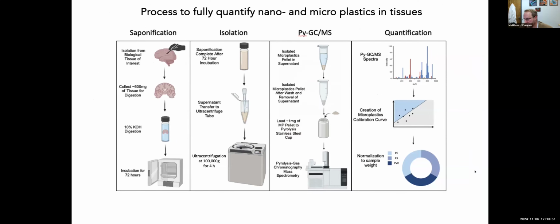So we developed a more cumulative approach for capturing all of the plastics independent of size, using a spectrometric method to do this. If you're familiar with Breaking Bad, the TV show about New Mexico, this is what we do to tissues out here. We put them into either an acid or a base, and we digest everything away that is biological. Essentially, we're using potassium hydroxide, turning the tissues into soap. We then spin out the solid remaining particulates, which is plastic and some small rocks, but mostly plastic. And there's some other biologics that are not fully digested, and I'll touch on that.